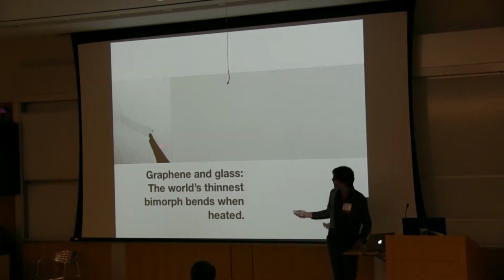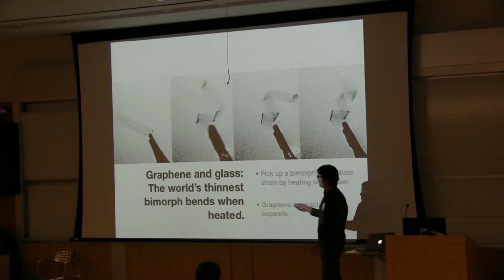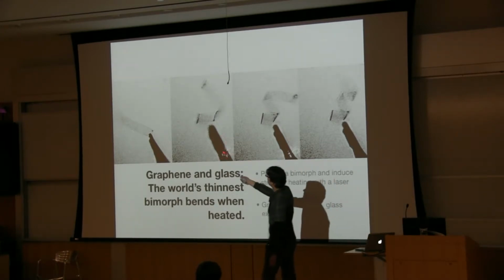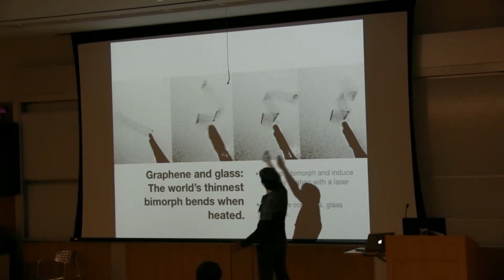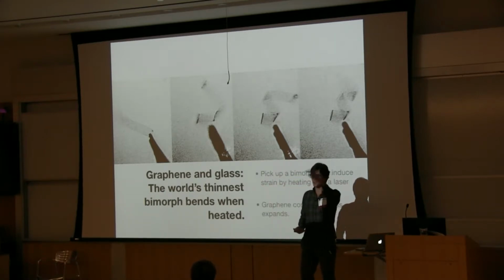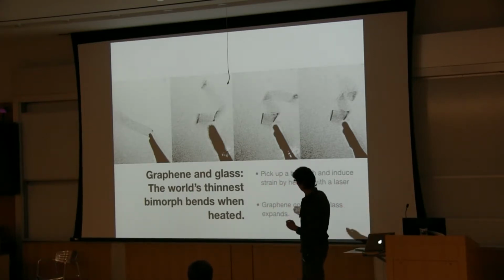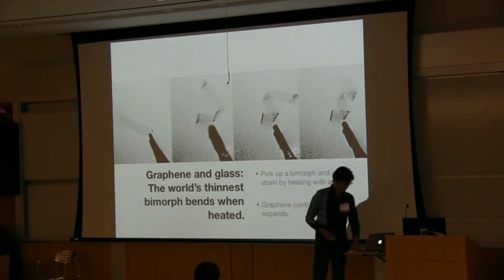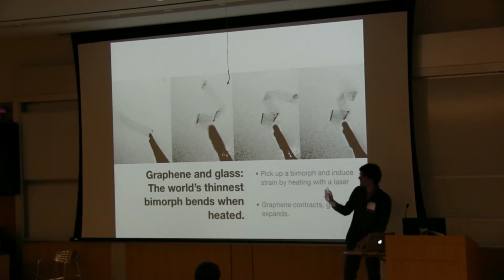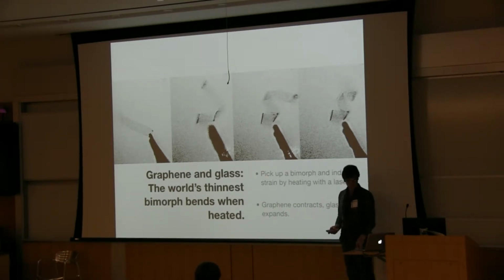So what we did is we picked up one of these devices. We're holding it with a tungsten probe. And I zapped the tungsten probe with a laser, and that heats the probe. The heat's conducted into the bimorph, and lo and behold, the thing bends. So it just curls itself up. In this case, the graphene is contracting relative to the glass, and you get a curvature that's proportional to the temperature. So minor victory, we've done it, we've made the world's thinnest bimorph, this thing works.